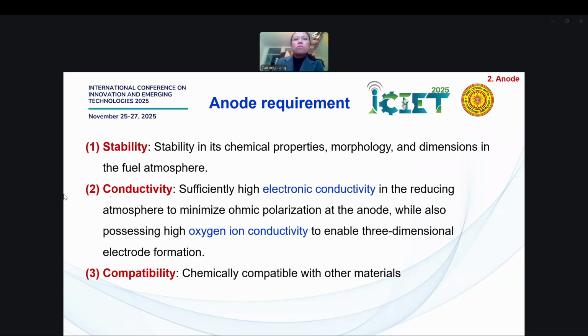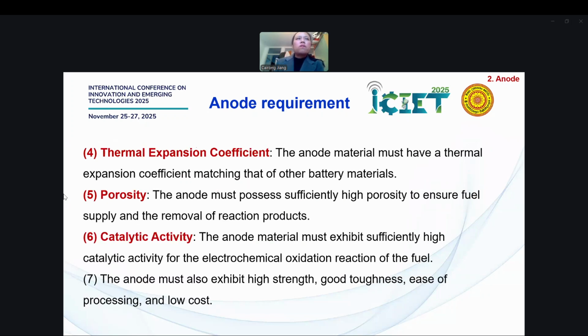And the third requirement is compatibility. All the materials must be chemically compatible with each other. Otherwise, during either the preparation procedure or the operation process, the cell will be destroyed or just collapse, and it's quite hard to maintain for a long time. And the fourth one, the thermal expansion coefficient, is understandable. It must have matching values for each composition.